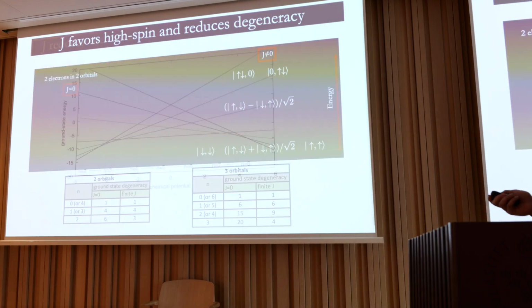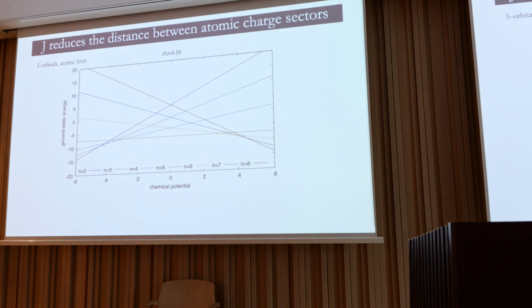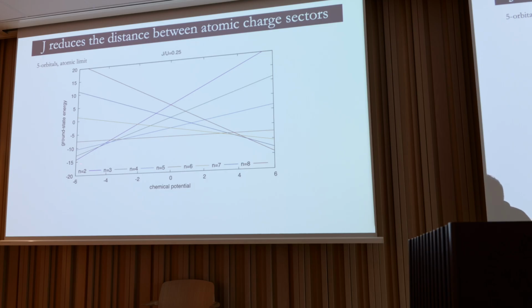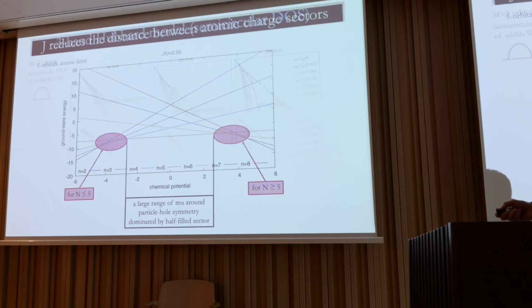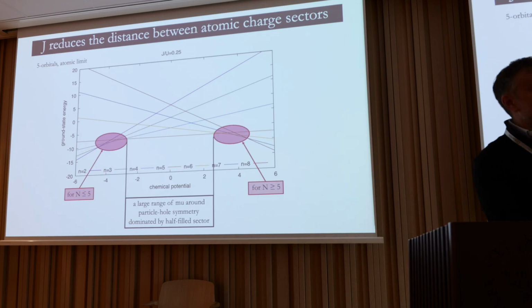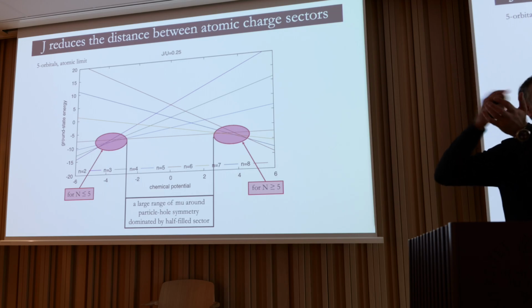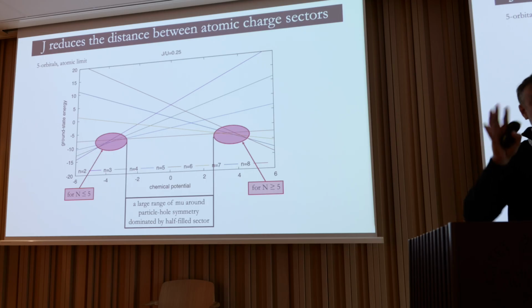Another thing that Hund's coupling does is change the distance between the charge sectors, because we are in metals and we have fluctuations. This is a complicated graph, but it tells you, as a function of the chemical potential, where your ground state is with 2 electrons, 3 electrons, 4 electrons, and this is half filling, so 5 electrons in 5 bands. Hund's coupling makes these charge sectors very close, so you can fluctuate easily between all the sectors below half filling, or between all the sectors above half filling, but then makes half filling really dominant, in the sense that there is a long plateau of chemical potentials where the atom wants to be half filled. So half filling is a special case because all the other sectors are brought close, so the charge fluctuations are easy, but the half-filled sector is brought far away from the others in terms of energy, and this makes it special.